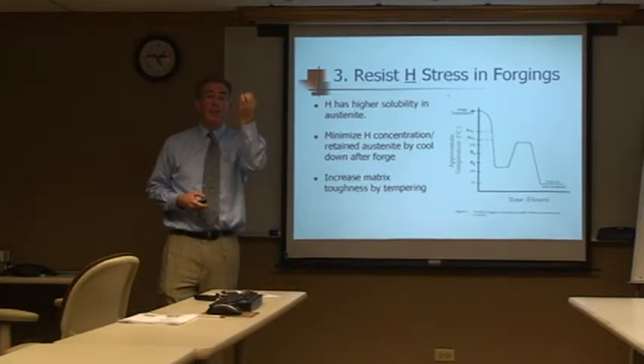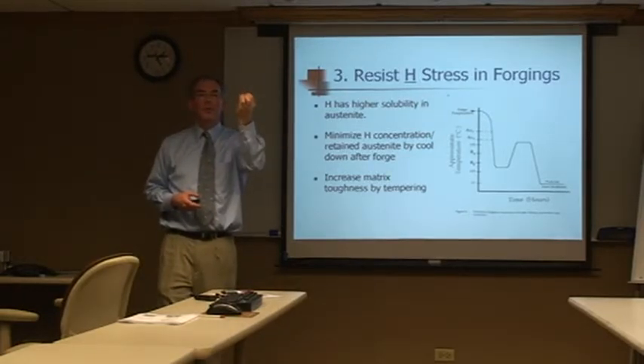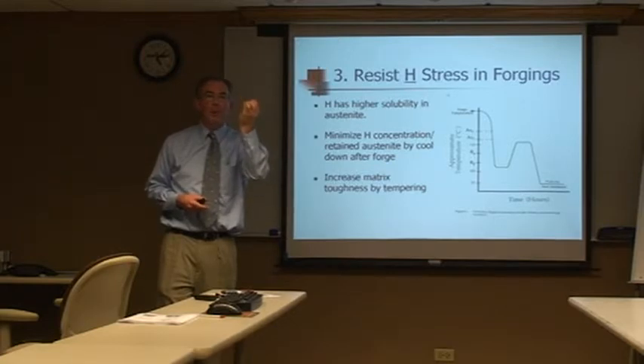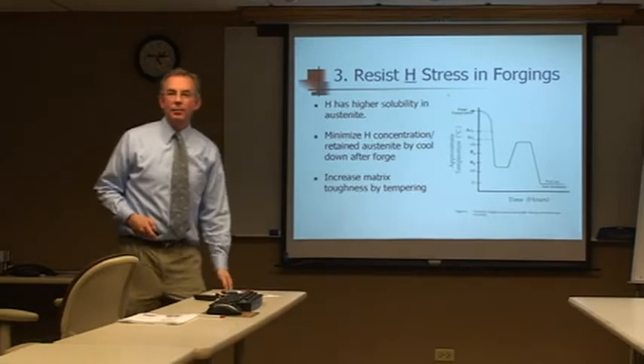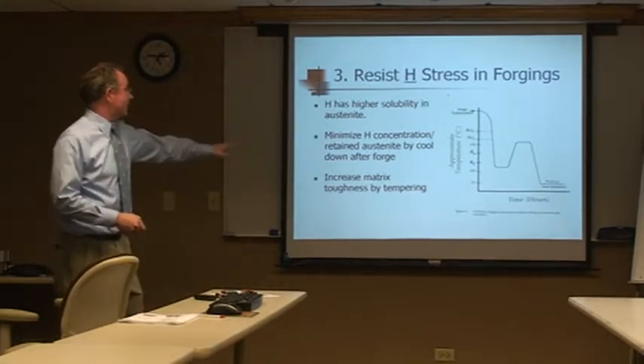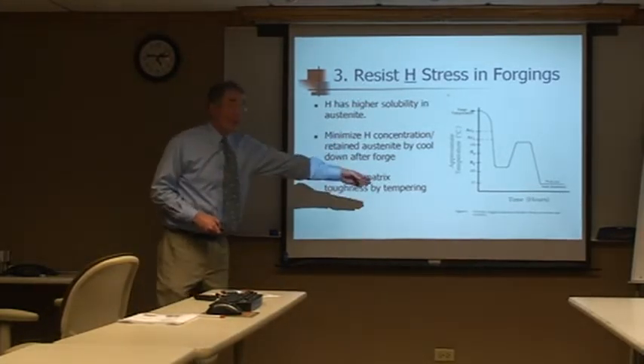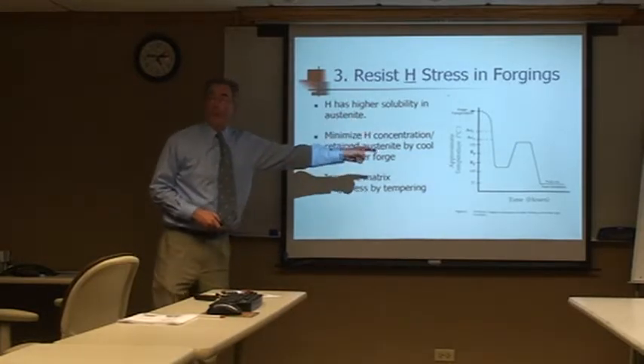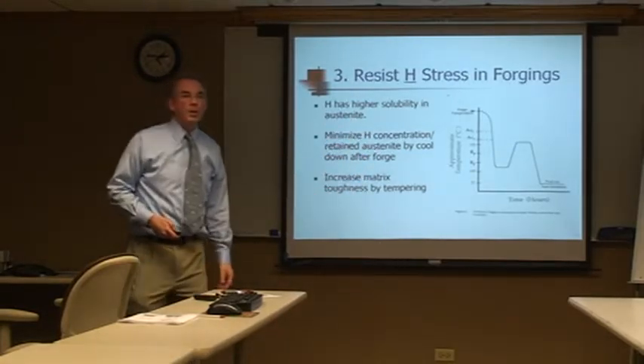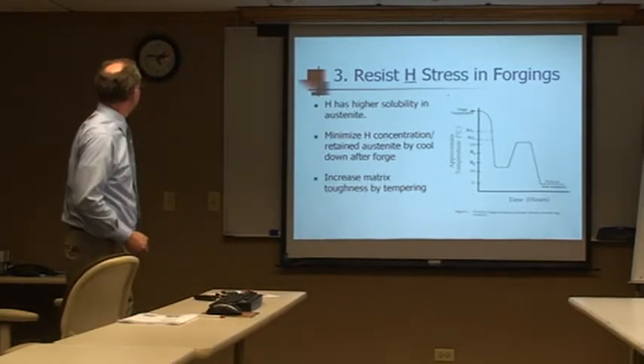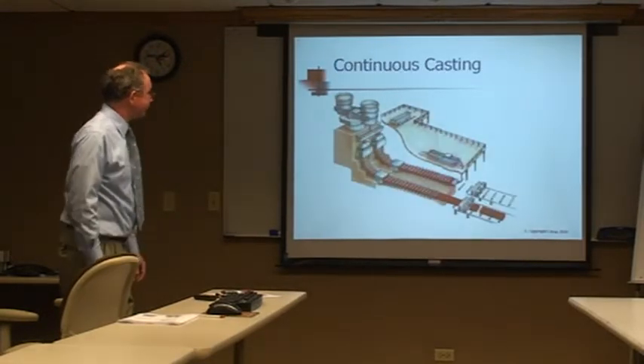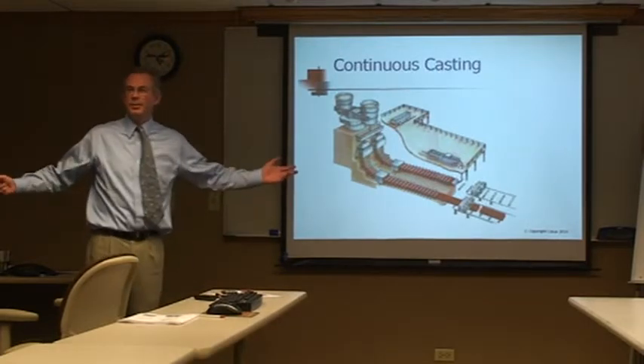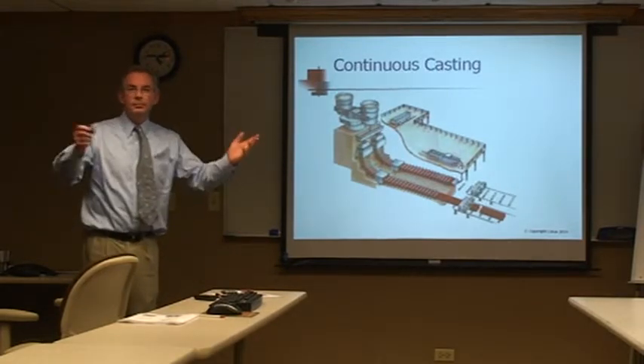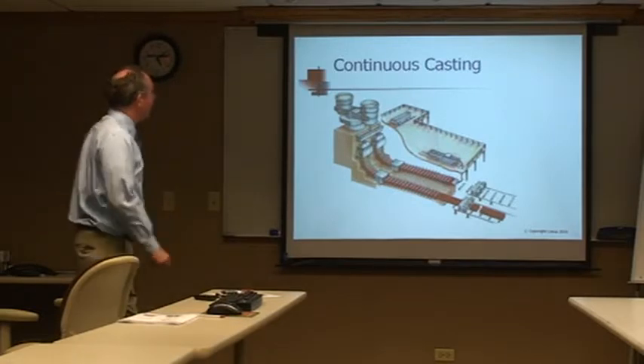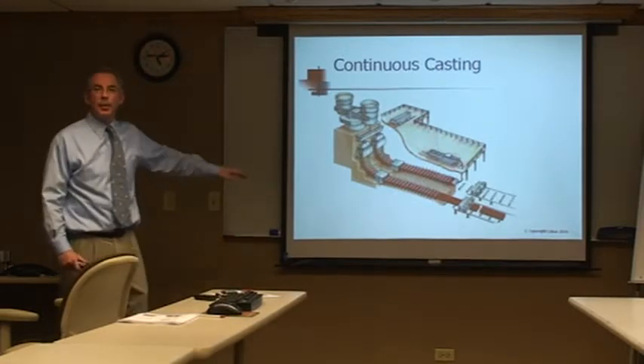And eventually, over time, this retained austenite transforms to martensite. Very hard, very brittle, and at that point, it can crack and also create hydrogen flake. So the matrix, by cooling, preventing retained austenite, and then tempering the matrix, making it resilient, is very important to resist hydrogen stress in forging. Make sense? Any questions? No? Okay. We're going past 5, I'm sorry.